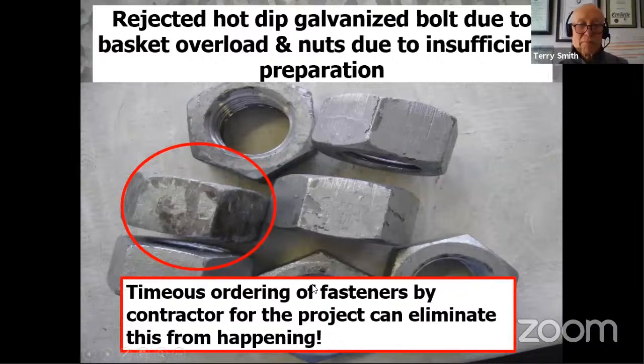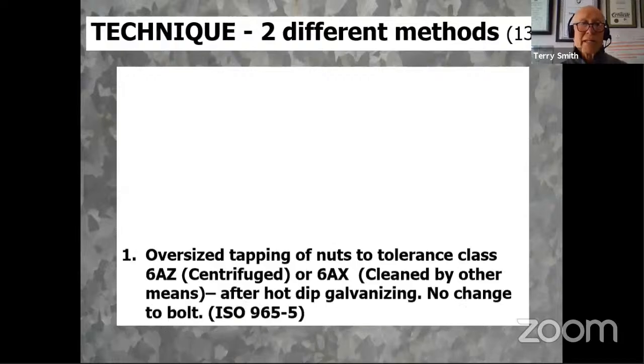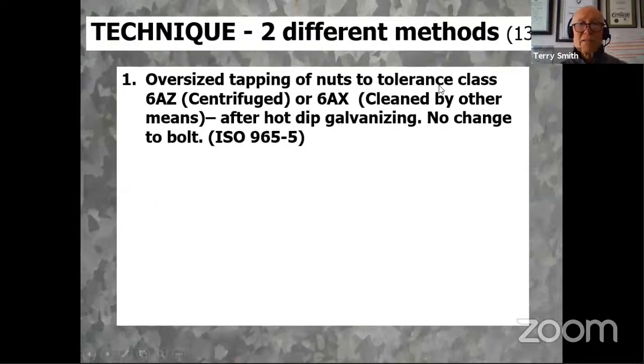So very important part, and this is extremely important for you guys as specifiers. The timely ordering of fasteners by the contractor for the project can eliminate a lot of this from happening. What we find often, the project starts, the items are fabricated and then galvanized, and at the last minute the bolts are ordered, and the guys are put under serious constraints by having to galvanize sophisticated fasteners for the project itself. The technique: oversized tapping of nuts to tolerance class 6AZ for centrifuge.